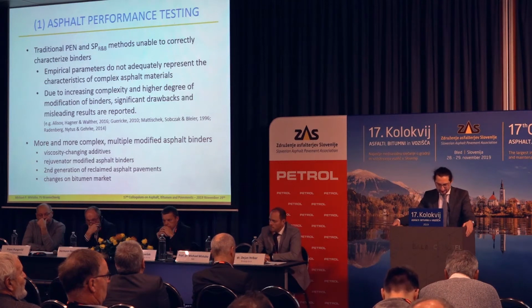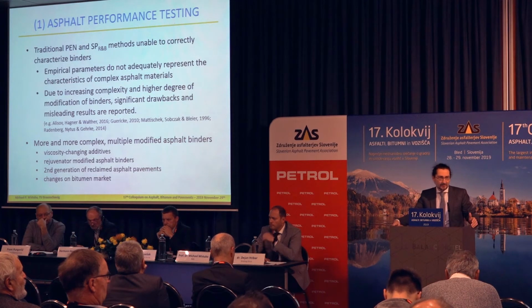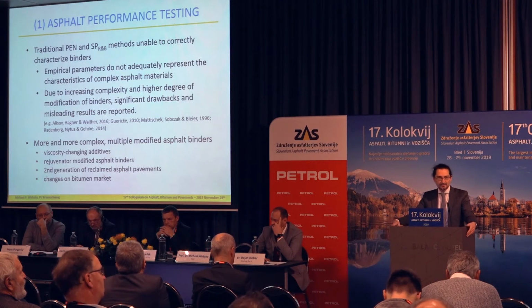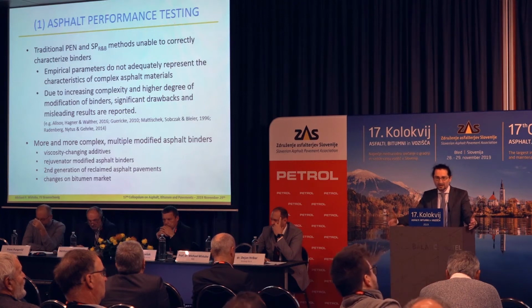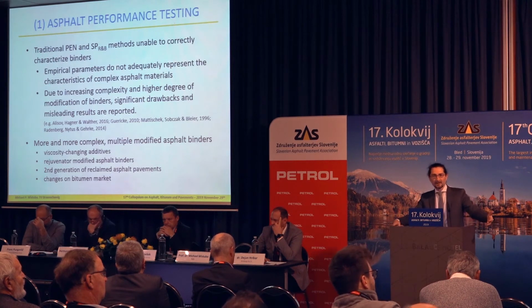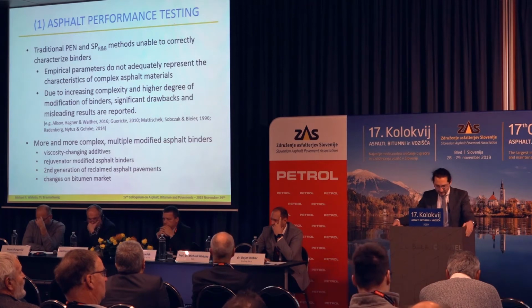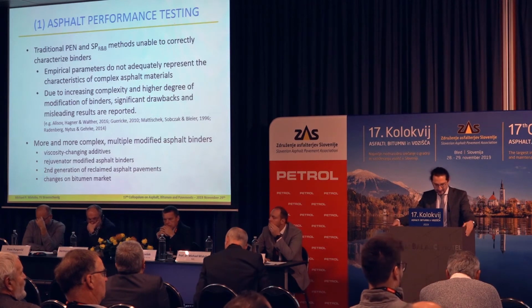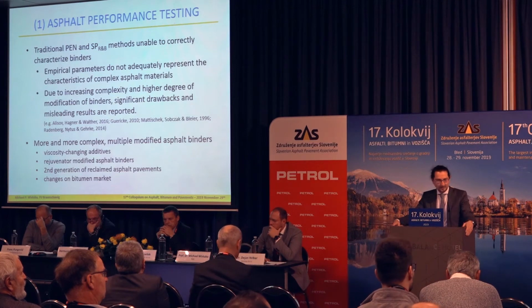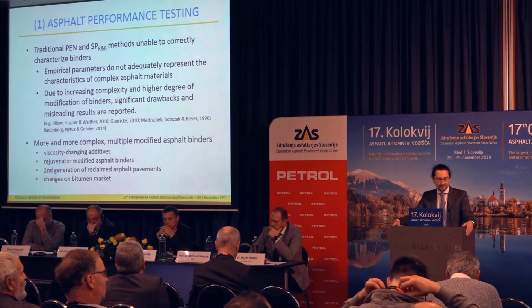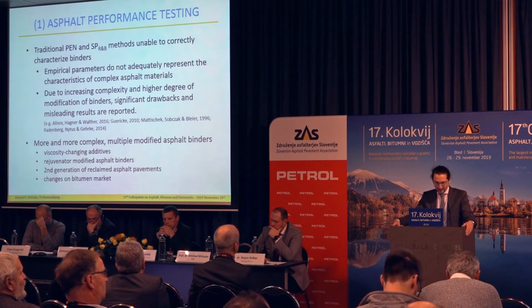But the problem is that these parameters, such as needle penetration and softening point ring and ball, were derived for plain binders, and they work for plain binders only. For modified binders, they do not work properly anymore. They are unsuitable for modified binders, and we see difficult results, or results difficult to interpret, as, for instance, regards polymer modified binders and the softening point ring and ball.